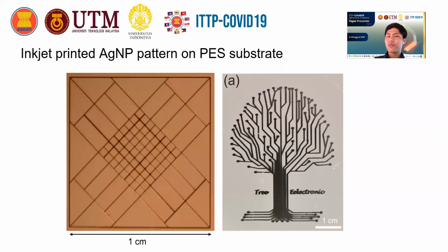After we have the printing substrate, we use an inkjet printer to print a micro pattern here. It's totally 1 centimeter square, and we print many just to show that our printing substrate is very nice and provides high resolution. We print silver nanoparticle ink to make a silver nanoparticle pattern, or AgNP pattern, and we provide some other designs, like a tree-like electronic design, just to show that when you have an application, you have the design of those circuits, and you can simply design and print them using an inkjet printer on our printing substrate. But you need to design your application. For us, we haven't designed the printing application yet.